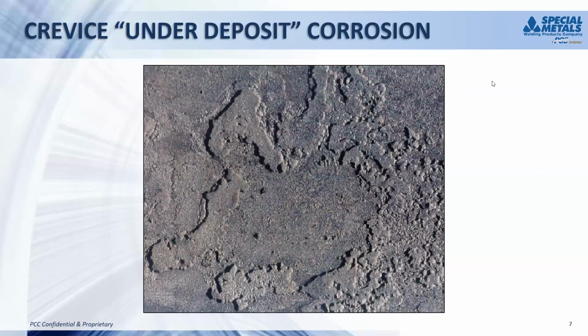crevice corrosion is another, more aggressive type of corrosion, actually more aggressive than pitting itself. We sometimes refer to this as under-deposit corrosion because in the FGD systems, a mineral deposit can form on the wall. Underneath that, the micro-environment can be very aggressive. Brian showed a slide of a boiler tube with a deposit there and how the halides, chlorides, fluorides, whatever, can concentrate below that deposit. We see exactly the same thing in FGD systems. So under the deposit, it will be high chlorides, high fluorides, and very low pH, which results in very, very rapid corrosion.